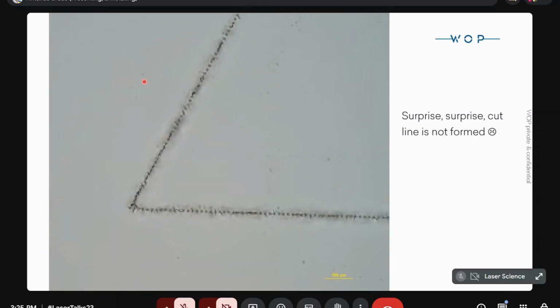And what happens if you try to make dicing with such a badly shaped beam? Surprise, surprise, a cut line cannot be formed, because these cracks inside of the volume are in very different directions at each spot, and they simply cannot join. And this is a line of separate modifications, but no single cutting line.